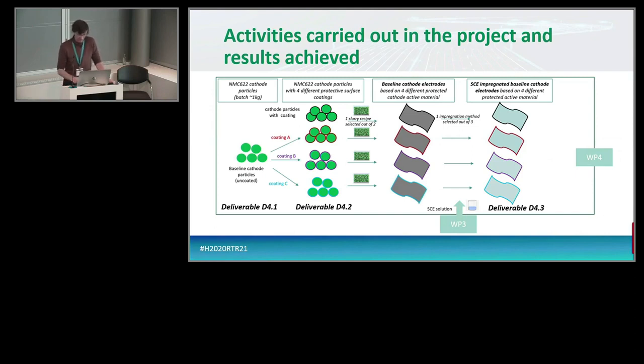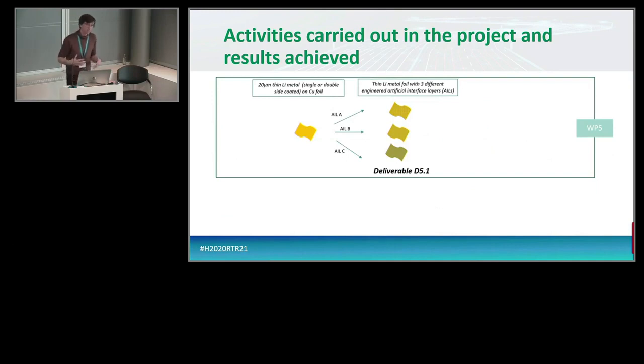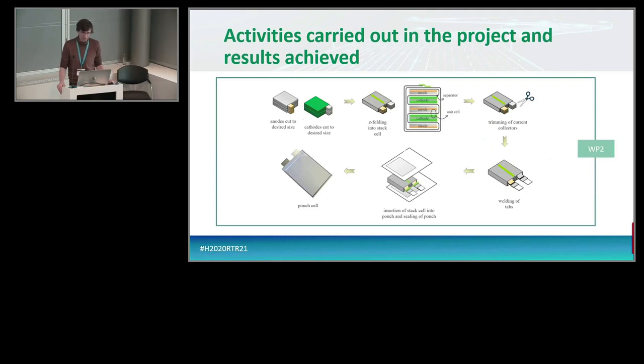And then again, we have different impregnated cathode materials, and one of these has now been selected to put into a cell. And last but not least, a similar approach also for the lithium metal. It's not a question of just putting lithium metal in contact with solid electrolytes. Lithium is very reactive and will react with basically everything. So also there you need coatings, a bit similar to the cathode. But here other partners worked on the coating for the lithium anode. Basically it was EMPA from Switzerland and IMEC that worked on different what we call artificial interface layers, with the goal to have a good, stable interface between the lithium metal anode and the SCE, the solid electrolyte. Again, 3 types have been evaluated. One of them has been selected and is going to be put in a cell right now. I only show here a very schematic of the cell integration. So basically you are putting everything together in pouch cells with the goal to make these first demonstrator cells that we have promised and that we have committed to within this project.